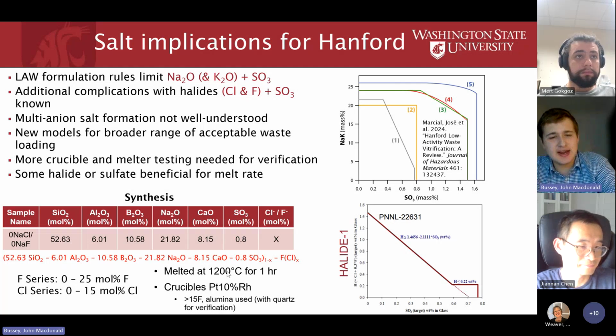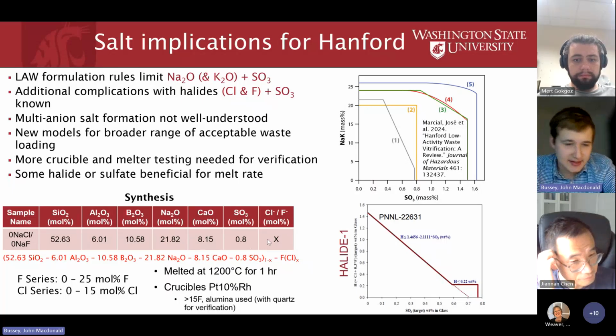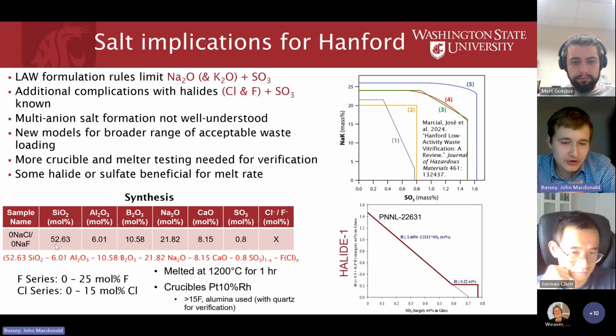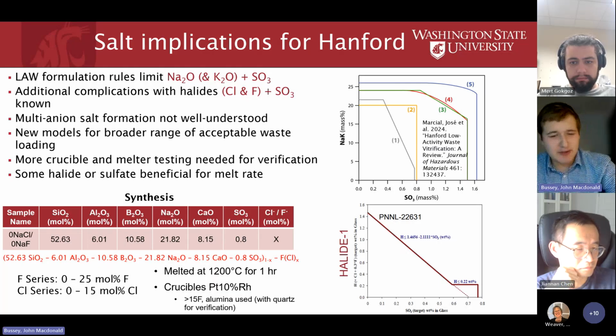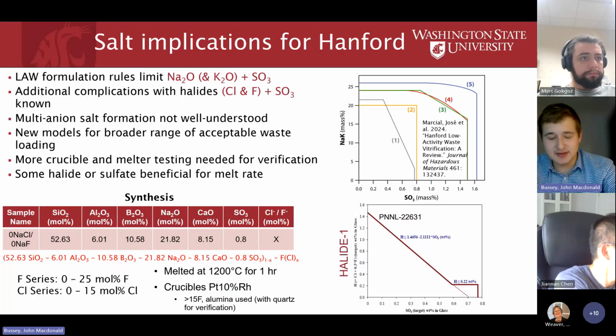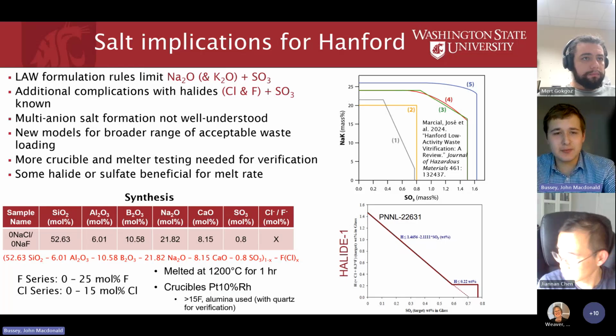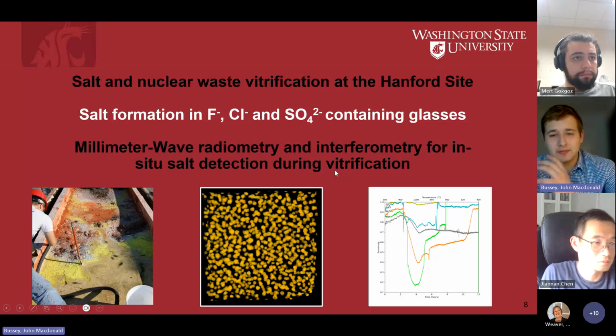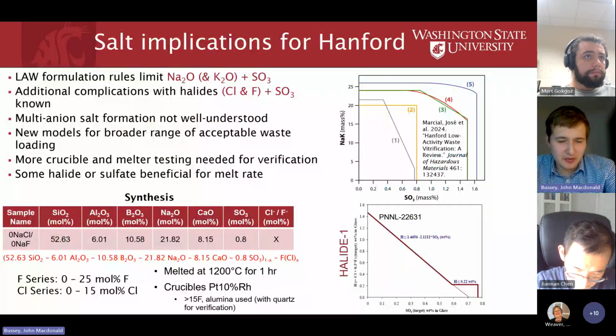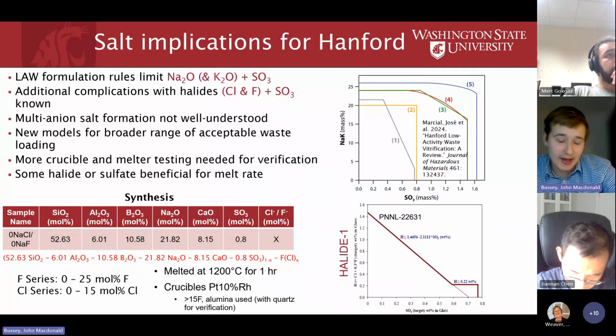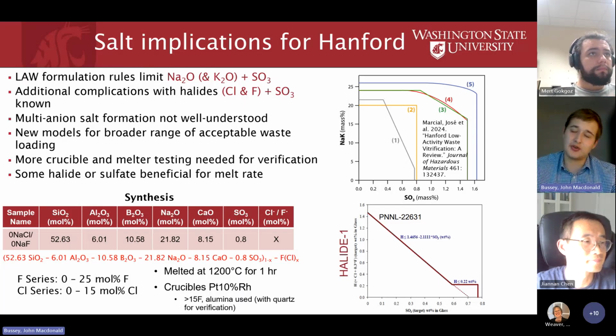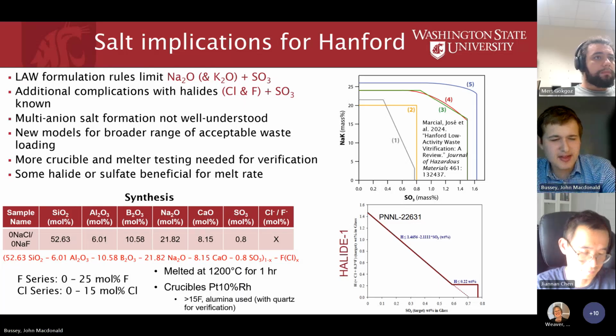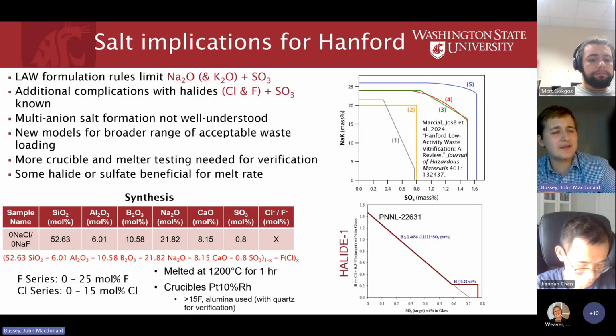So we designed, well, not me, Natalie in her PhD designed this series of glasses to test these things. This was right at the end of her PhD, and I helped her make the glass, and then she promptly left with this pile of glasses and no characterization. So what did we make? They were made at 1200, so slightly above the operating temperature at Hanford, which is 1150. We made them in platinum crucibles, using a simulant mixture with no radioactive elements. Outside of a lot of the more minor components, we chose the main things that affect glass forming ability, and then varied fluorine and chlorine to test their incorporation.